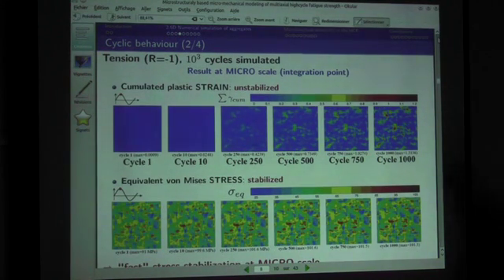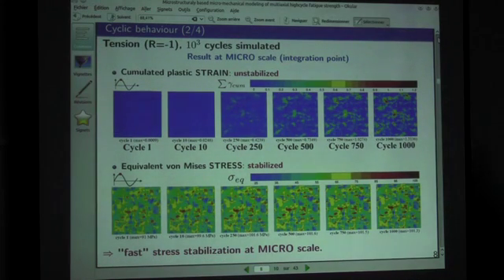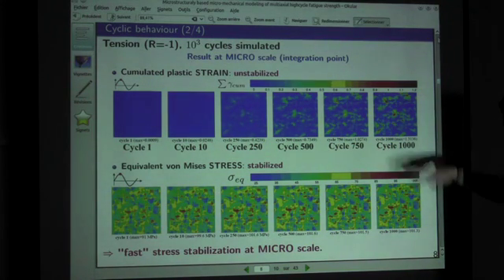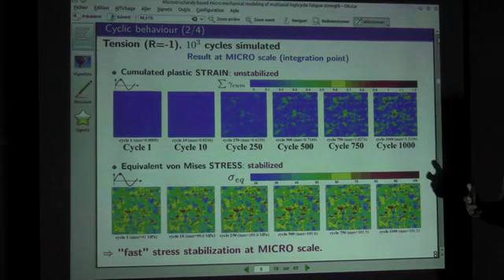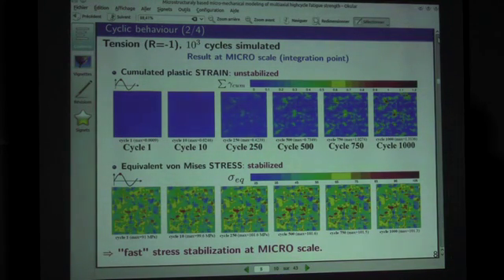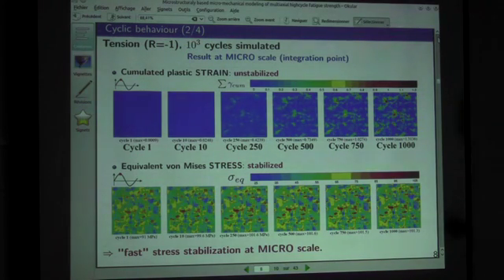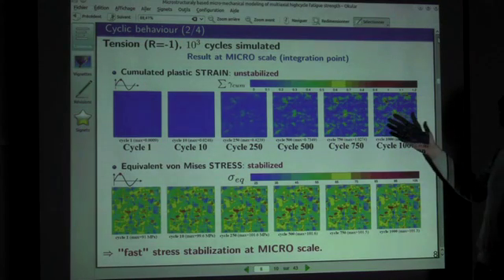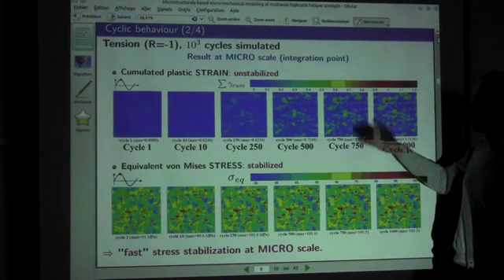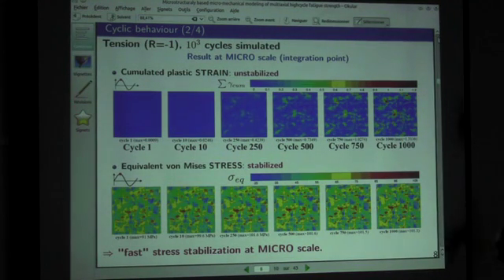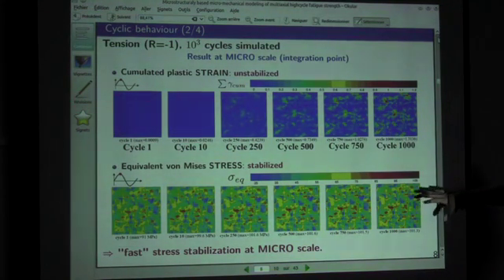at different evolution of the stress and strain during cyclic loading. So this is computational results that we did for different loading cases. Here it's in tension, and we simulate 10 to 3 cycles, so 1,000 cycles, and we try to see what is the evolution of the local stress and strain with respect to the constitutive behavior that we have been inputting in the model. So what we can see is that you have a constant evolution of plasticity parameter, which is normal, accumulated plasticity progressing along with the computation, while the stress quantities, which is here a picture of the equivalent stress, von Mises equivalent stress, is more or less stabilized quickly.